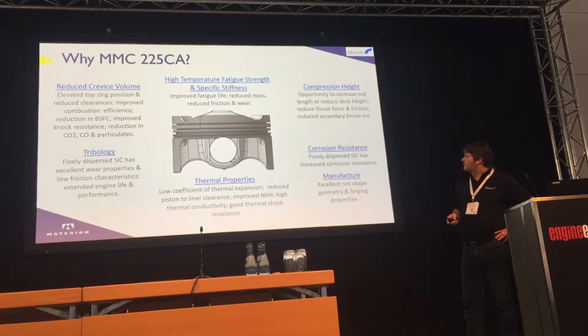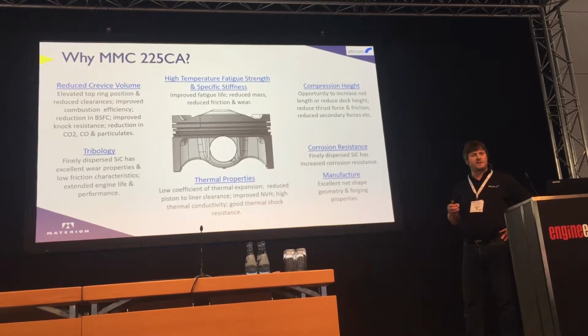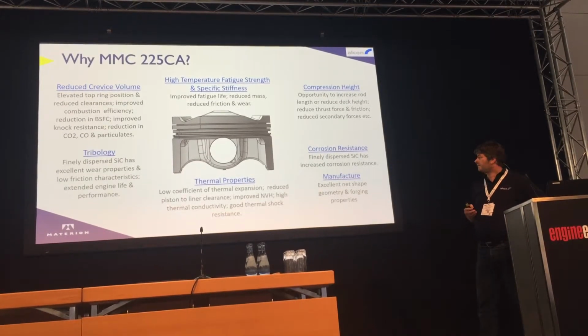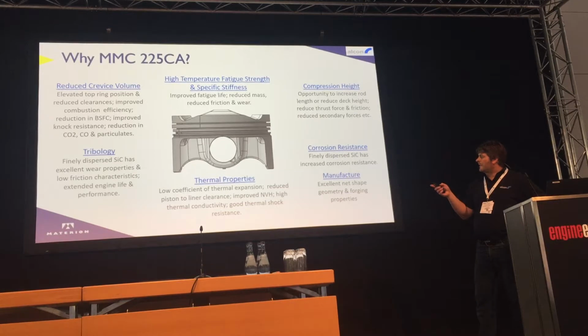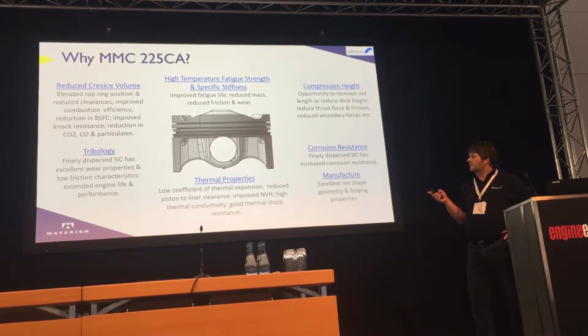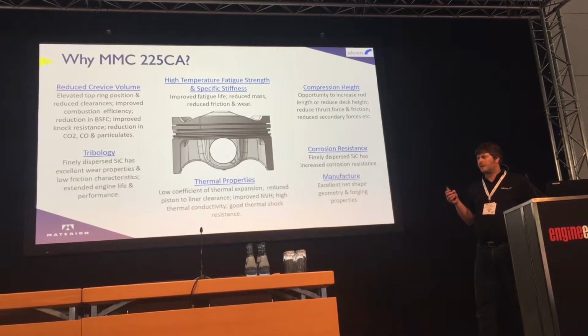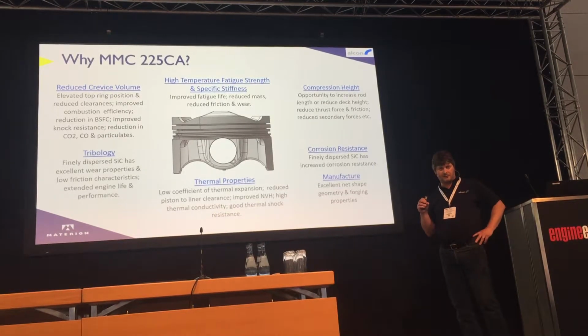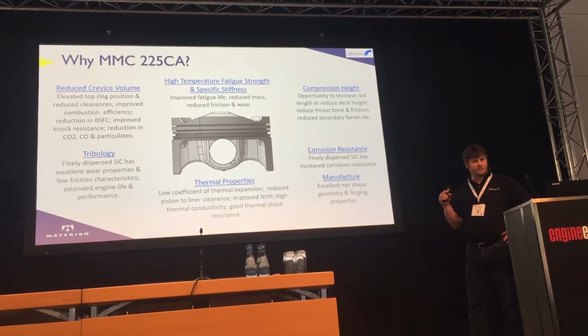So very good high temperature fatigue strength. The specific stiffness is a lot higher as well, so that for the same fatigue strength as a standard alloy, you can basically reduce mass. One of the main things we also look at is reducing the crevice volume. And what we've been able to achieve, especially on high specific output engines, is a much smaller crevice volume.